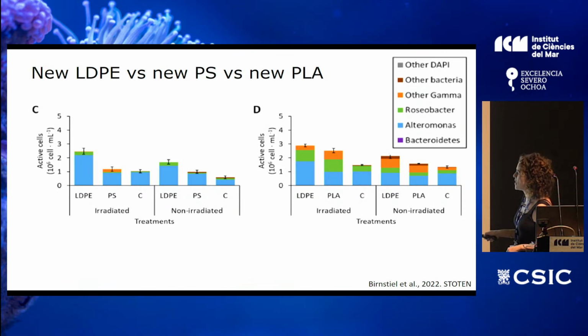Here, this is the number of active cells, and this is the contribution of the phylogenetic groups to this activity. Okay, so we saw here that the LDPE was the treatment where more active cells were. Here, both plastics, PLA and LDPE, were more active than the control without plastic. And in some cases, there were no differences between the control and the plastic. And then the predominant phylogenetic groups were Alteromonas, Roseobacter, and other gamma proteobacteria. Here there was more abundance of the other, and here more of the Alteromonas.